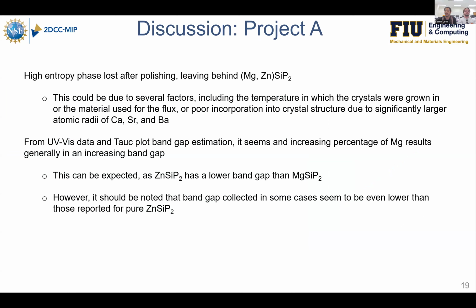A little bit of discussion on why some of the Project A samples were a bit difficult to fully synthesize. One thing we expect could be the cause for the high entropy phase not really incorporating, or crystallizing, the way we wanted to is that there is a very large difference in the atomic radii of the elements, especially since we're just going down the column of the alkaline earth metals. I think the greatest range of difference between the atomic radii is about 65 picometers, so it's pretty large.